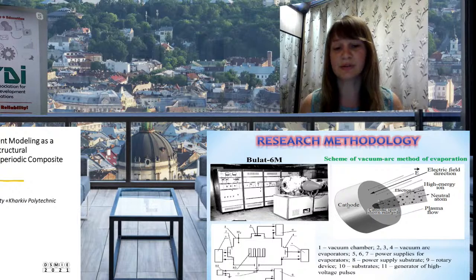Coatings were obtained on the modernized installation Bulat 6M, which was additionally equipped with a generator of high voltage pulses applied to the substrate during the deposition process. The pressure of the working atmosphere during the deposition of nitride layers was about 0.6 Pascal. Structural investigation of the samples was carried out using the installation DRON-3M, and in all investigations copper alpha radiation was used. Next slide.